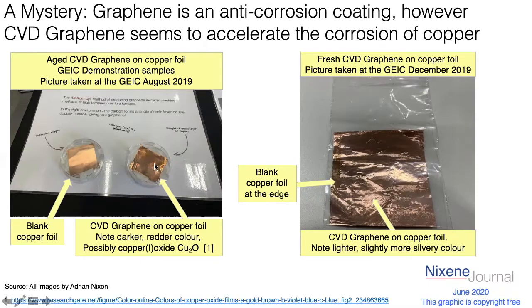So that sample there and this sample here should be the same, more or less. They're both copper foil. They're both coated with a one-atom-thick layer of graphene, yet one is darker and the other is lighter. The main difference is this sample here is fresh. It was only made a few weeks before we saw it, and the CVD graphene coating on the surface of the copper foil is protecting it. So it seems to be uncorroded, lighter and brighter. Yet over time, the graphene seems to be causing the copper to corrode. It's a bit of a mystery, isn't it? Yeah, it really is. It's what's making the difference between the two.